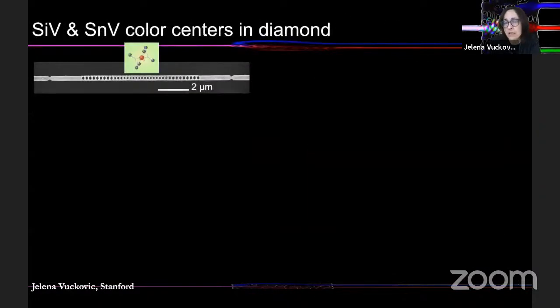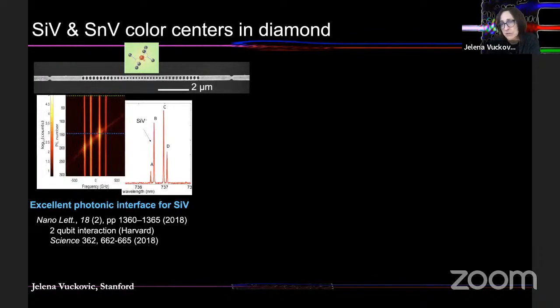So as I said, we're primarily working on color centers in diamond and in silicon carbide, and there are many different color centers that occur in these materials. In diamond, in particular, we're interested in group 4 impurities, which is at the moment silicon and tin vacancy color center. And if you look at the lattice of carbon atoms inside of diamond, these particular color centers are produced by removing 2 carbon atoms and adding an extra silicon or tin atom in between. And silicon vacancy color centers have been studied for a pretty long time, maybe about 10 years actively in the context of quantum information processing. And we made some interesting contributions there, and of course, many other groups.